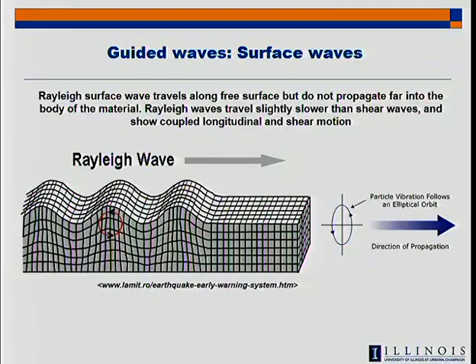And in this case, the wavelengths that we use are on the order of inches. So we are not penetrating very deep below that surface. We have a good idea of what's happening an inch or two below the surface. But if you have a serious problem on the backside, this approach is not going to see it, probably, honestly. So it's a surface detection system. Not ideal, but most deterioration mechanisms in concrete and timber start from the outside in, because the bad guys that are causing deterioration, moisture, UV, oxygen, come from the outside in. So if we can characterize the outside, we're still in good shape.